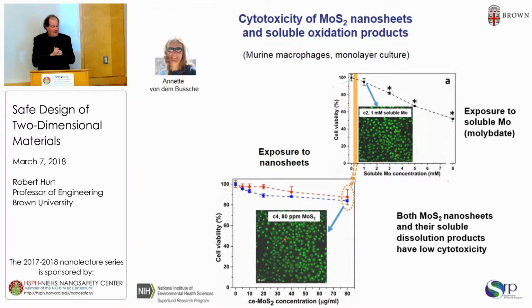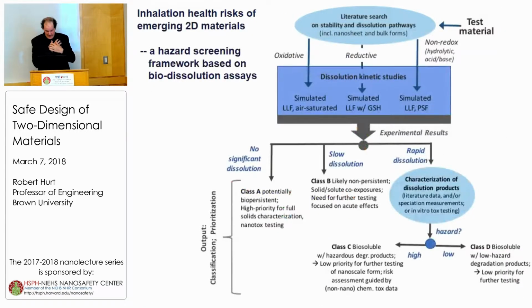nanotox studies. But it also opens up the possibility of using MoS2 in biomedical applications because of its programmed degradation. So something that degrades over the course of about a month could be used in various biomedical implants. It can go away over time, and both the sheets themselves and their soluble dissolution products are believed to have low toxicity. So it's an interesting way, as a spin-off of our work on environmental health, to identify a material that might be interesting for implantable technologies. So those are my two case studies.